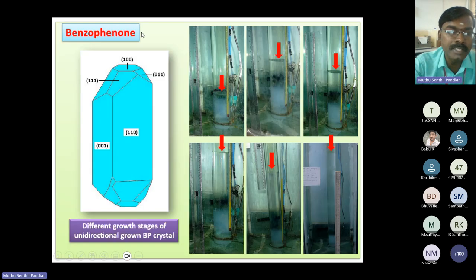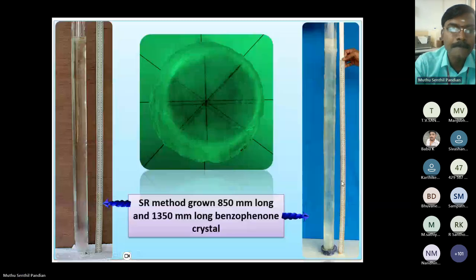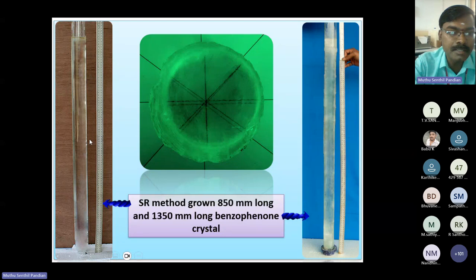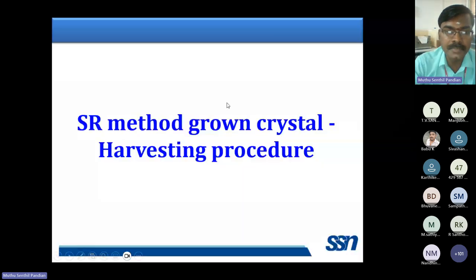So this is the morphology of benzophenone. We selected the A direction, the 100 direction, for the longest growth, because the growth rate along this direction is very high compared to all the other directions. These are the different growth stages of this world's longest benzophenone single crystal. The transparent portion is shown here. This is the 85 centimeter benzophenone. This is the 1350 mm longest benzophenone single crystal from this SR method. This is a double refraction pattern from this benzophenone single crystal.